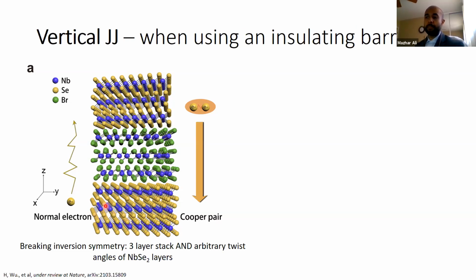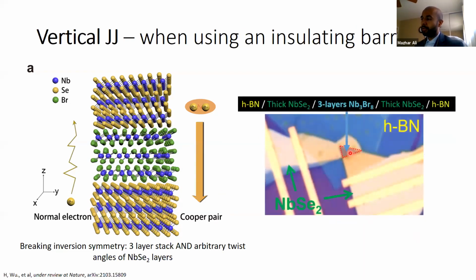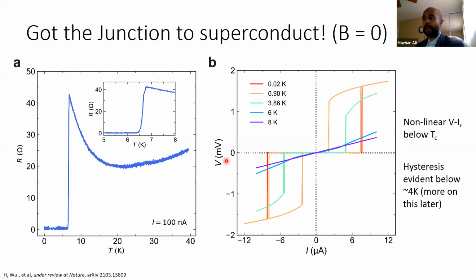So we were able to basically make ourselves a sandwich. We took our wafer, we put an underneath layer of NbSe2, then we put our 3 layers of Nb3Br8, then we put a top layer of NbSe2, and then we capped it with some hBN. So everything was all nicely protected from air and all of that. So very clean devices. And we got it to superconduct. We were actually able to tunnel across. So that was the big win, and that was very fun.